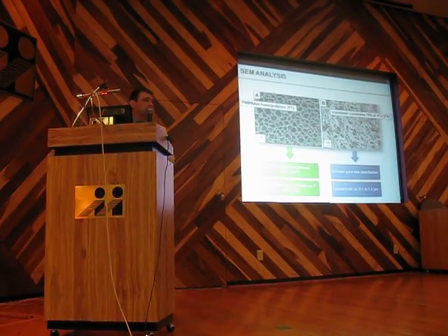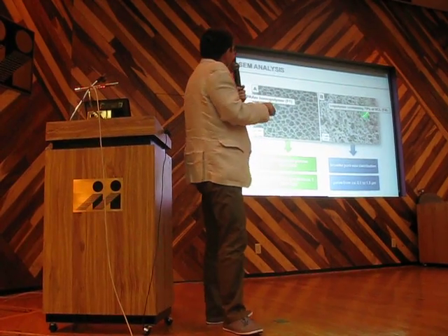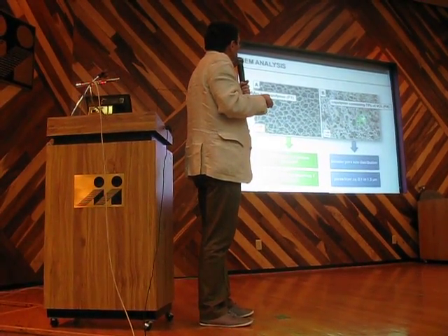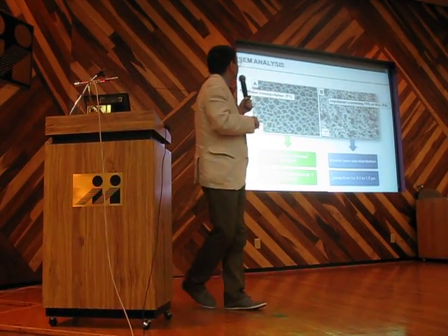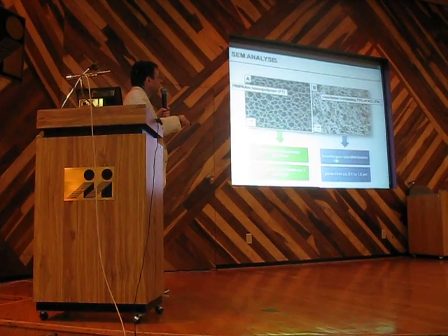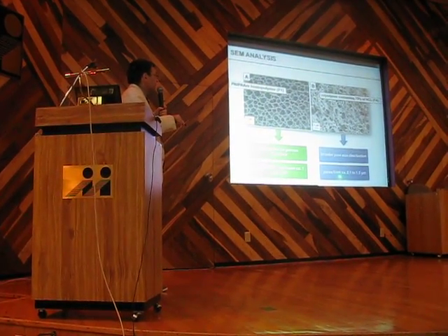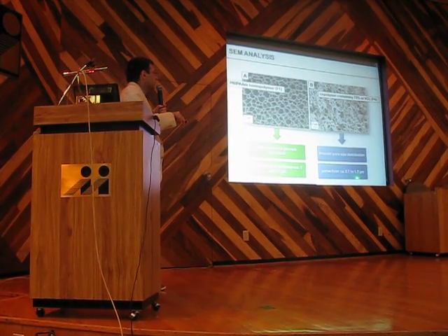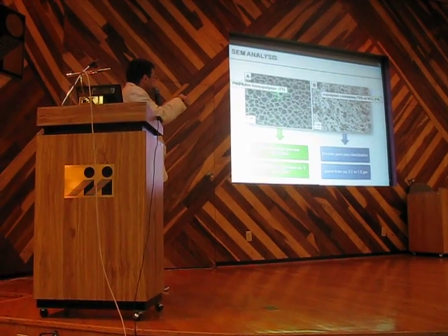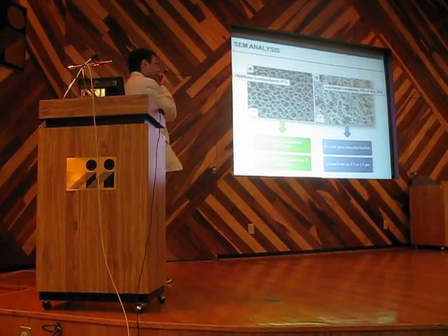We found it every time by using any method. And the situation is quite different if we have 25% of this other monomer. We have a broader pore size distribution, with pores in this case from 0.1 to 1.5 microns instead of pores here that are comprised between 1 and 2 microns.